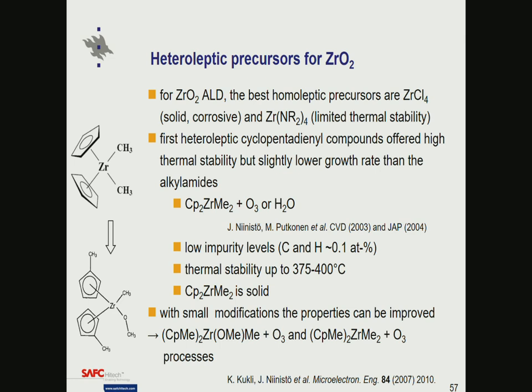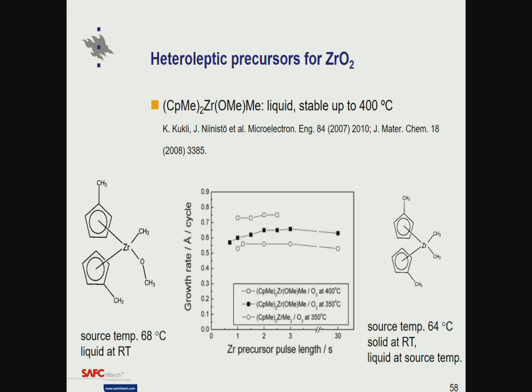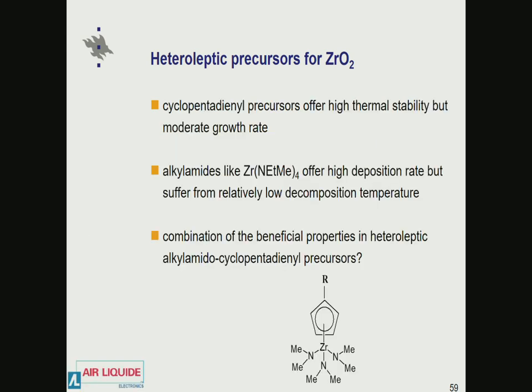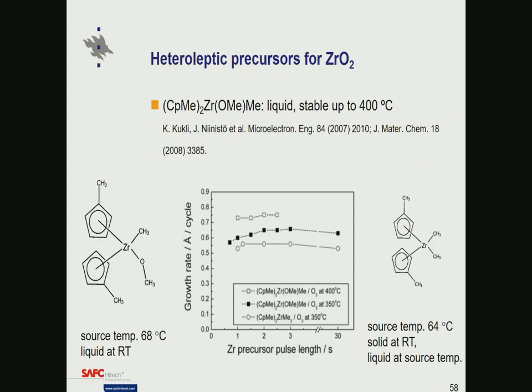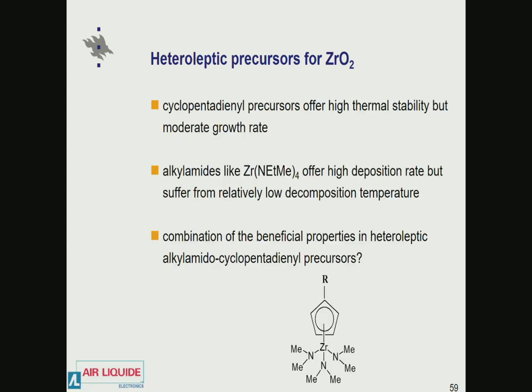But there was a problem that this was a solid. So the next step from here was that one of these methyl groups was replaced with a methoxide group. So now we actually have a metal complex with three kinds of ligands. And this turned out to be a rather good precursor. It's a liquid, stable up to 400 centigrades, so it's nice with saturation there, and gave rather good film growth as well. This being learned, the thinking was, okay, we have cyclopentadienyls which have this higher thermal stability as shown here, but the growth rates were still leaving room for improvement. It was also known that alkylamides do exhibit a higher deposition rate, but they suffer from low decomposition temperatures. And then the question is, if we combine these, can something better be created?